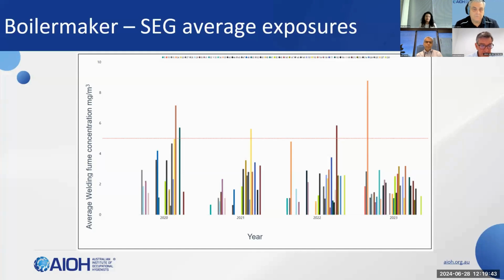This data typically includes full shift monitoring data. Each colour represents a different mine or a different site. Each of the vertical bars represents the average concentration of welding fume exposure to welders in the boilermaker group. The previous exposure limit is indicated by a dotted line at 5 milligrams per cubic metre, and you can see that the levels are consistently below this. But remember, these are average concentrations, and many of the single sample levels are much higher than this, and particularly the UCL 95% values often go above the 5 milligram per cubic metre limit.